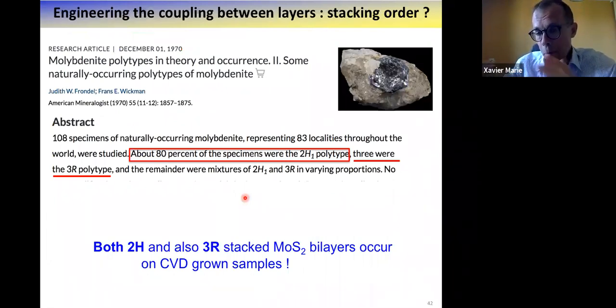So how can we compare a homobilayer with 2H or 3R stacking? You can just start from what nature gives you. If you look at the mineralogy papers, and people who know very well molybdenite from mines, it tells you that in nature, the two polytypes exist, but 80% is the 2H polytype, and a few percent is indeed 3R, because in terms of energy, as people who do calculations know, the two configurations are rather close to each other. So even in nature, you can find 3R stacking. And what we realized with the work performed with a colleague in Jena is that when you grow bilayers with CVD, if you look carefully, you will find some bilayers with 2H stacking and some with 3R, a little bit like you have in nature. So thanks to that, you can do measurements.